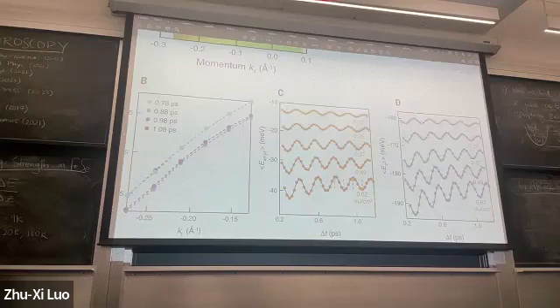But here you're comparing the change of band structure. Yeah, so this is the band structure actually oscillating. So that's in that picture there. The X-ray experiment is telling us about the selenium oscillations. That's an experiment with a way faster time scale than the oscillations of the band structure, right? No, the key is that they happen at the same time scale because there is a strong coupling between the phonons and the electrons. And I'm confused by that picture.